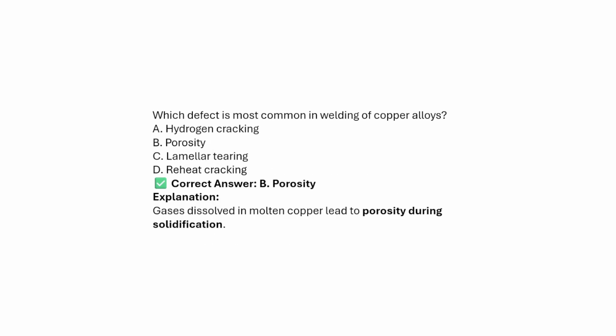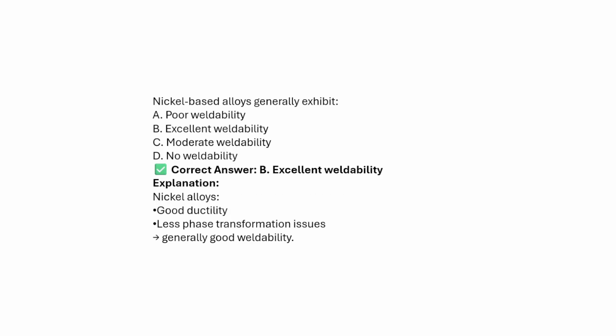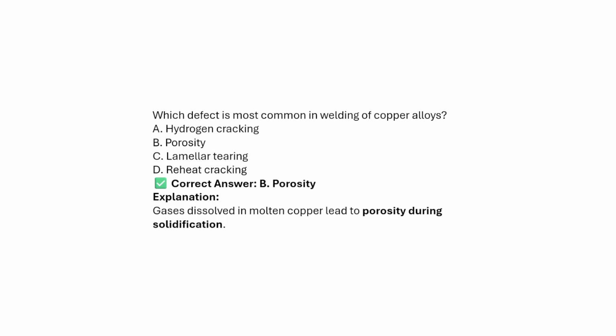Nickel based alloys generally exhibit... Which defect is most common in the welding of copper alloys? Hydrogen cracking, porosity, lamellar tearing, reheat cracking. The answer will be porosity. Gases dissolved in the molten copper lead to porosity during solidification.